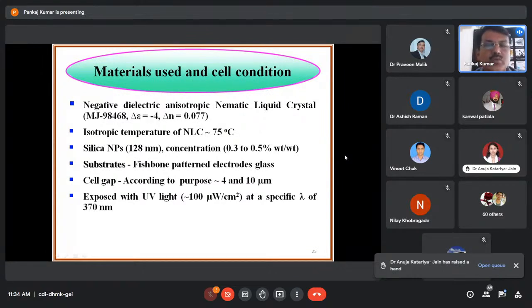So we wanted to confirm whether every substrate is giving the vertical alignment or not. So the cell gaps were 4 micrometer and 10 micrometer, and here to control the pre-tilt angle of the liquid crystals, we use UV light of 100 microwatt per centimeter square at a specific wavelength of 370 nanometer.